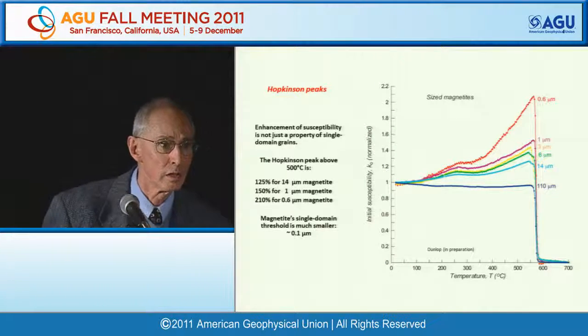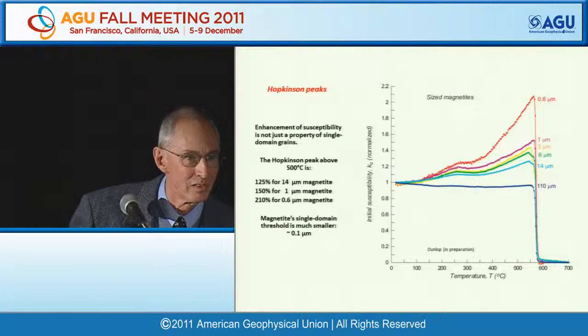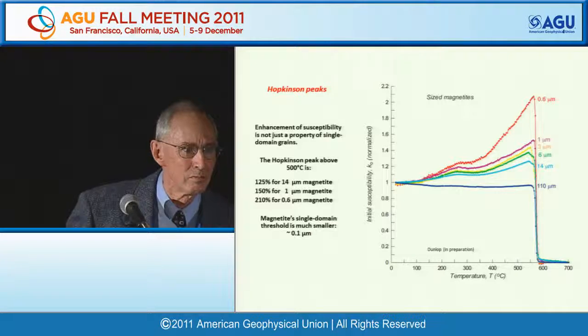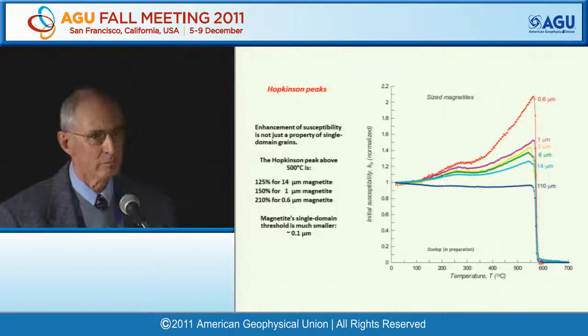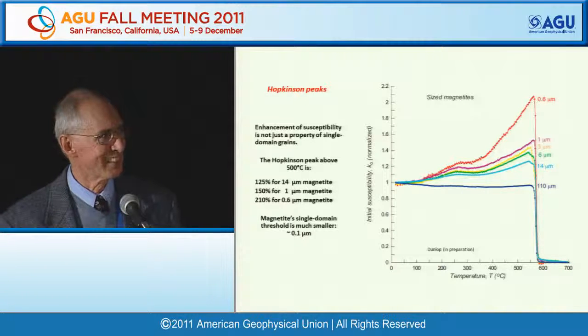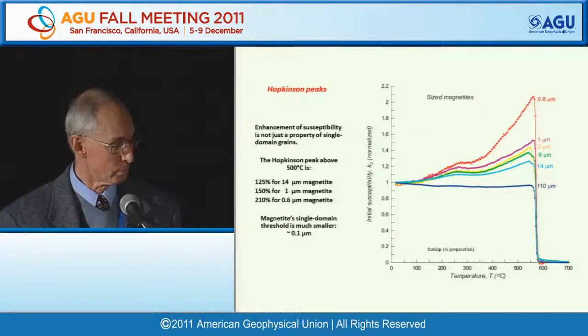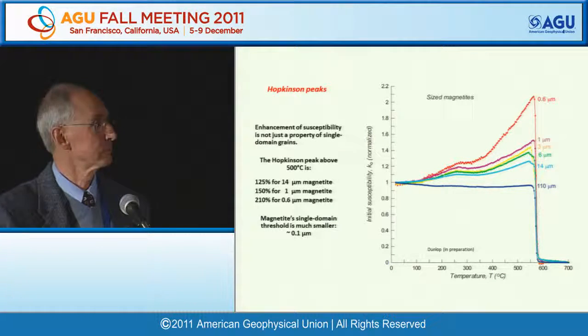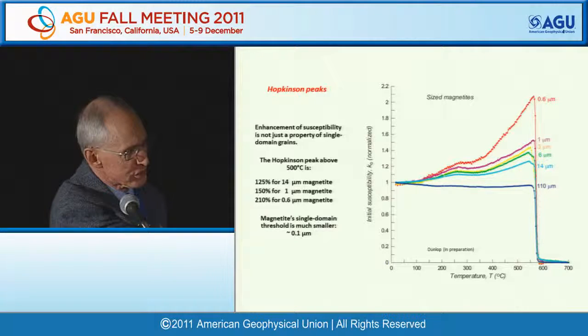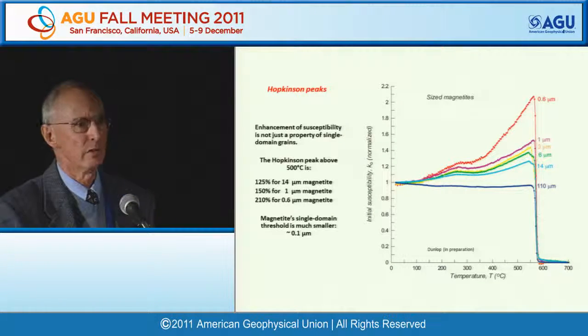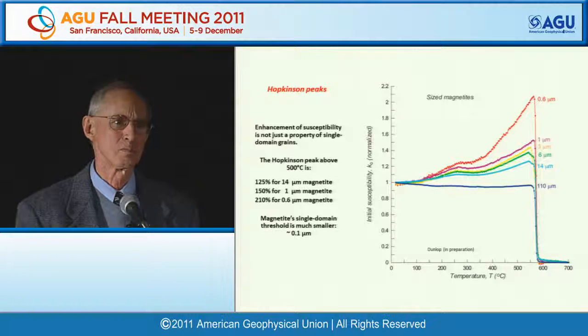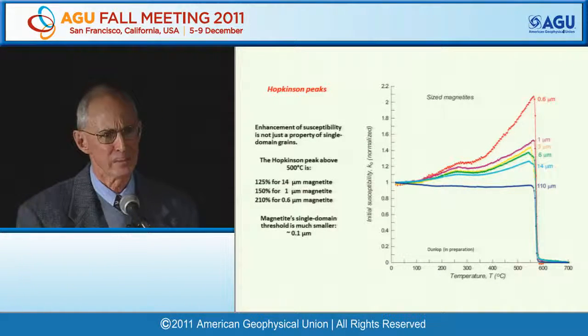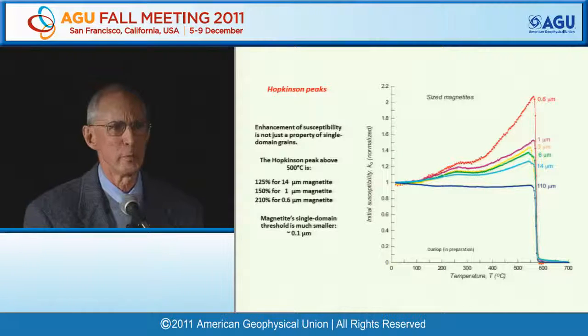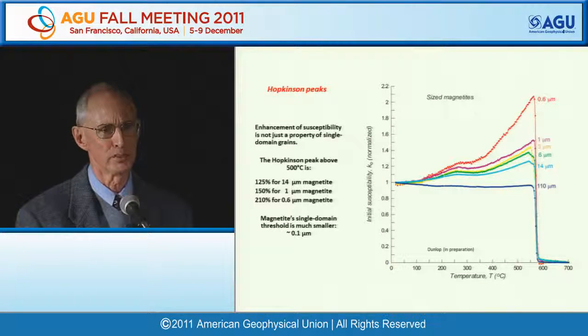Richard? Okay, the question is, there is the high temperature Hopkinson peak, but also in these data, you always see a subsidiary lower temperature peak. No, that is due to the fact that these magnetites were not heat treated in advance. If you do this experiment a second time, that lower temperature peak goes away. It's due to stress. These are synthetic samples.